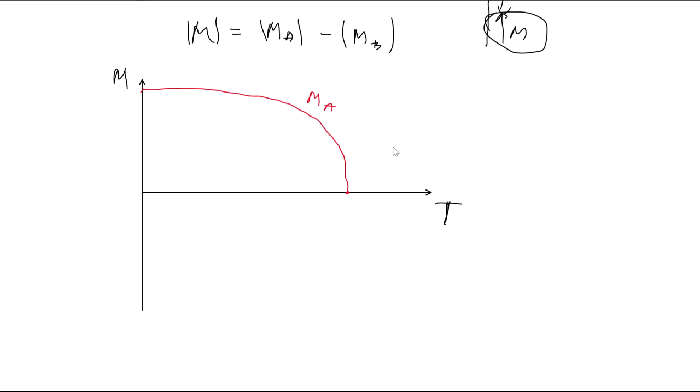So as we cool the ferrimagnet above Curie temperature, we have a paramagnetic state, which means that the interaction is not strong enough to overcome thermal energy. Thermal energy overcomes the interaction between magnetic moments, and the material becomes ordered below. So above, thermal energy is high and we have a totally random magnetization. Now the interesting part is that we have this sublattice A and B. Let me draw it again here. So we have big A, small B. This is B, this is A.